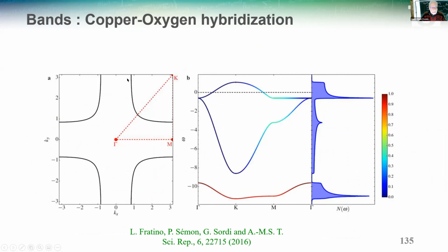So on the left is the Brillouin zone, and the Fermi surface is these solid lines. And let's move along a path here from gamma, K, M, gamma. There are 3 orbitals per unit cell now, so there are 3 bands, right? You need to diagonalize these 3 by 3 matrices. The lowest band is mostly copper. It's in red. And if you look at the bands near the other bands, they are mostly oxygen.